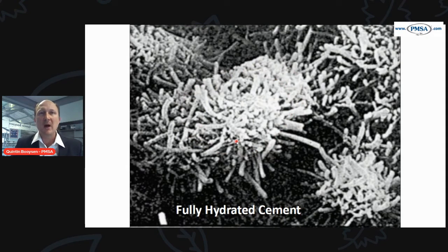So under a microscope, we are looking at the gel formation, the little fingers that start coming off inside of the concrete, between all the particles of sand and all the particles of other materials. You have this incredible gel structure that starts forming, and these little fingers start crossing across to each other, and they are the basis for the strength that you're going to form inside of your concrete.